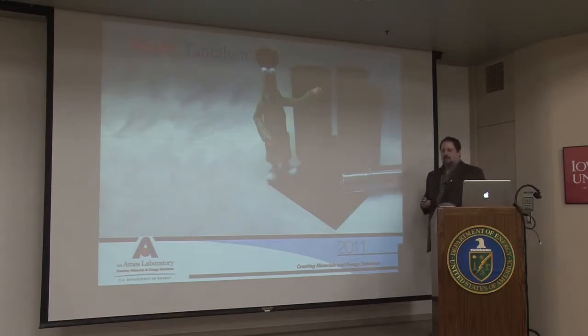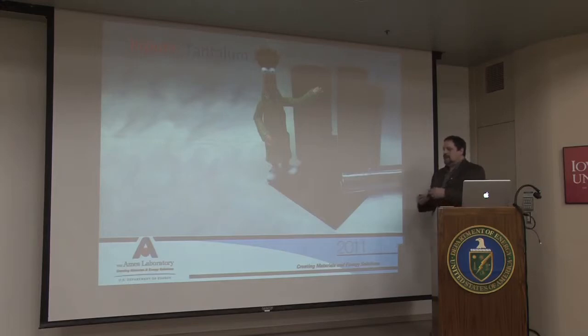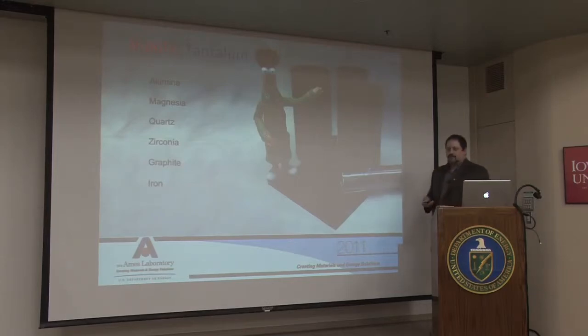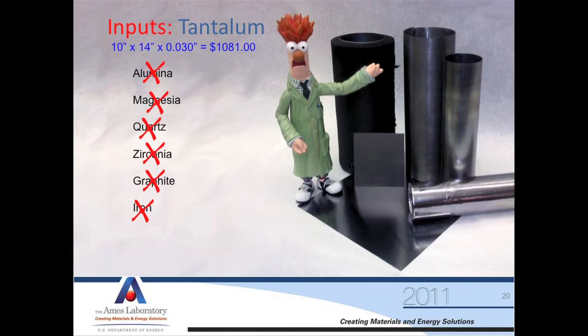Tantalum is one of our inputs, and I couldn't get any of my technicians to pose for a picture holding a tantalum crucible, so we had to use our mascot beaker here. Tantalum doesn't chemically help us make the rare earth by reducing anything — it is simply the crucible material, the bowl in which we cook our dinner. There are lots of options for crucible materials: alumina, magnesia, quartz, and several others. However, the rare earths are some of the most reactive materials available, with some of the highest free energy of formation of oxides — in other words, they'd rather be an oxide than anything else. So most oxide-based crucibles are unusable. We could use graphite, but the rare earths love graphite. A lot of metals you can cast in iron — no, can't do that with the rare earths. So we're left with tantalum. Problem is, tantalum is very expensive: a 10 by 10 sheet about 30 mils thick costs about a thousand dollars, and you'll get to use it once or twice before you're done with it.